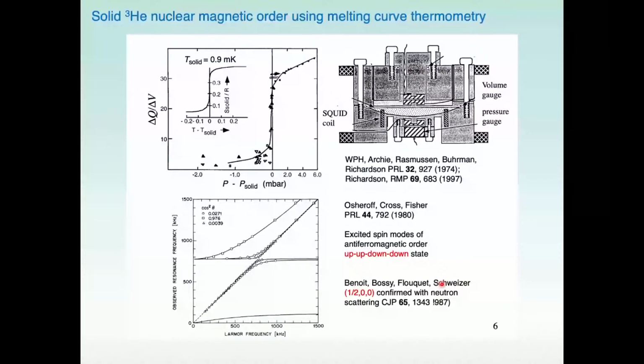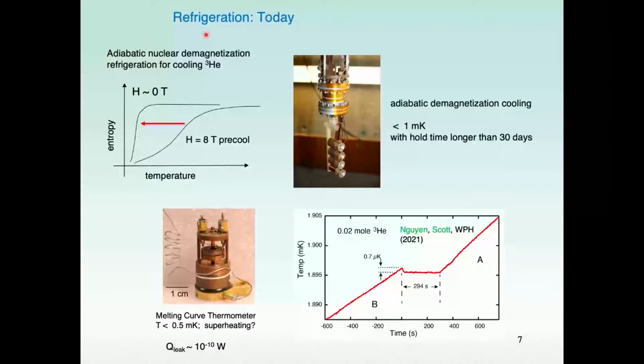Now, that's not the way refrigeration is done today. I warrant that there's not many Pomeranchuk refrigeration tools being used. Rather, it's nuclear demagnetization, which is the powerful way to cool superfluid helium-3 to extremely low temperatures. And here I want to just mention that the adiabatic demagnetization, say at Northwestern, using the coolant praseodymium nickel 5, can hold below 1 millikelvin of temperature for a period of time of 30 days. This is the sample cell, which I'm showing for illustration.